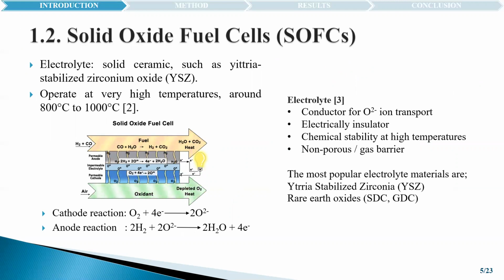They use a hard, non-porous ceramic compound as electrolyte, such as yttria-stabilized zirconia. An electrolyte carries the oxygen ion between electrodes and therefore directly affects the cell performance. The most popular electrolyte material is yttria-stabilized zirconia, but it is not the best ionic conductor for SOFCs. Ceria-based materials show better conductivity, and rare earth oxides such as samarium oxide as dopant in ceria produce maximum conductivity. This is why in our work we studied 20 mole percent samarium doped ceria materials as electrolytes.